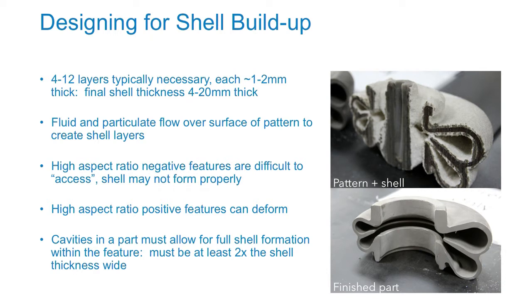So the structure that you're making has to, in addition to being stiff enough to satisfy the requirements of its service life, also withstand the process of being submerged into that ceramic slurry, being rotated, being handled when it's realized in a much more delicate material. These printed PMMA patterns are kind of the consistency of a sugar cube, a little bit lighter, so you can definitely scratch and abrade material away with a thumbnail. And it's relatively brittle, so very, very fine, thin features will break. So that's something to definitely keep in mind.